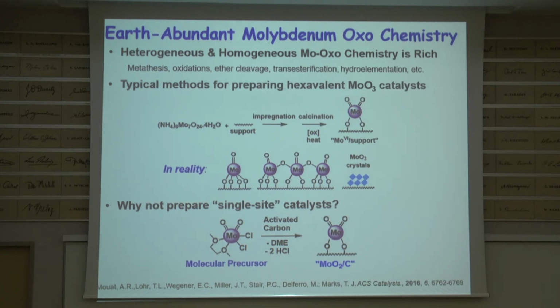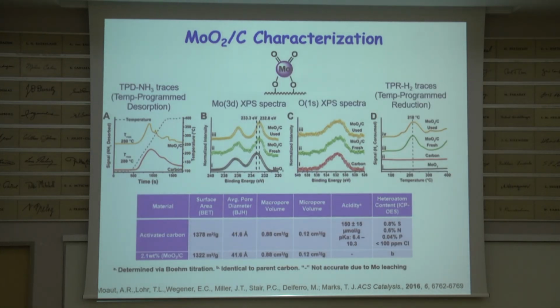activated carbon. And the state of the art, like the zirconium chemistry, has advanced enormously from the days when people would just dismiss your work as support effect. So you can do temperature programmed desorption to probe the acidic sites on the carbon, and then on the molybdenum complex on the carbon, X-ray photoelectron spectroscopy. You can look at the molybdenum by itself. You want to look at the carbon to make sure that there are no other species that would cause a problem. Oxygen can tell you a lot about the nuclearity of the metal oxides, and of course X-ray diffraction.